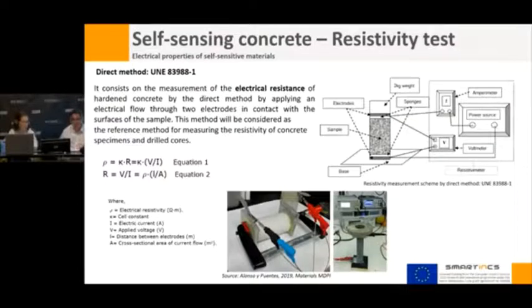To measure this parameter, two methods are used: the direct method and also the four-pole method. The first one, here in Spain, we use a standard that is mentioned here, which I think is now updated, but at that moment, in the Lorcenis project, we used this one. It consists of measuring the electrical resistance by applying the current between the two surfaces of the concrete sample, as you can see in the scheme that I put here in the presentation. From the electrical resistance measured, we calculate the resistivity by means of these equations.